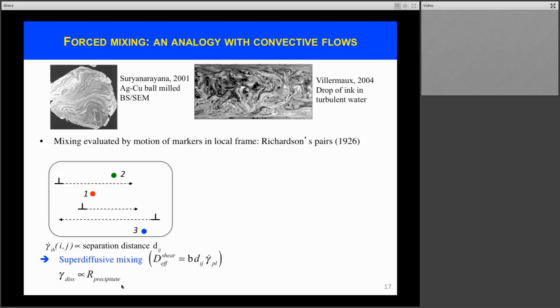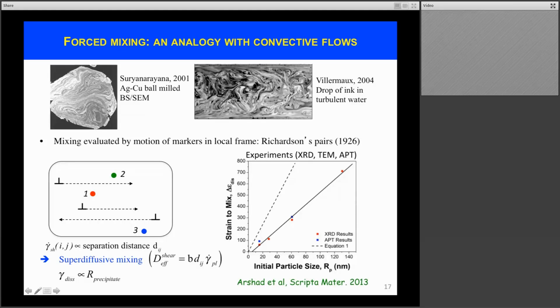One prediction from this super diffusive mixing is that if I had a precipitate here in the middle, the strain it would take to dissolve this precipitate scales linearly with the radius of the precipitate. And we tested this prediction by preparing materials with different silver precipitate size in copper, and so the red and blue squares are results from experiments, and the line is the fit through this equation here, up to a geometrical coefficient. We see that there is a very good agreement with this idea of super diffusive mixing.